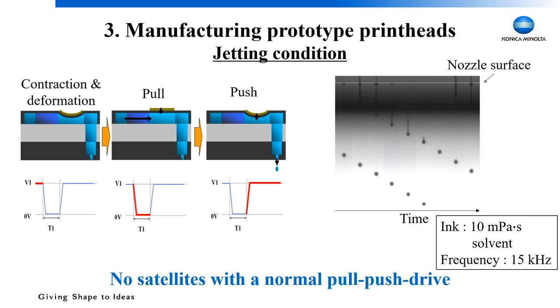This picture shows the jetting condition of a single nozzle. The horizontal axis means time. We used solvent ink with 10 millipascal-seconds viscosity and drove 6 meters per second at 15 kHz. We observed no satellites with a normal pull-push drive.